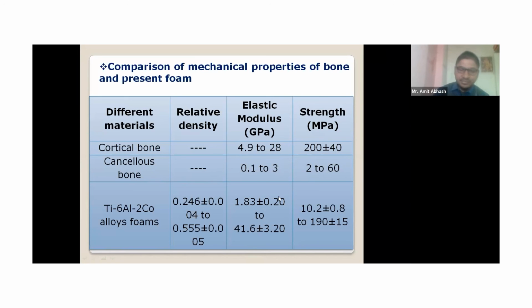Now, the prepared foam, in our case the Ti6Al2Co alloy foam that I have prepared, the relative density is varying in the range of this. Elastic modulus is the main part of concern. I have got this range, and this is an amazing range that I have got here. This much, 1.83 GPa is the elastic modulus, and it goes up to 41.6.